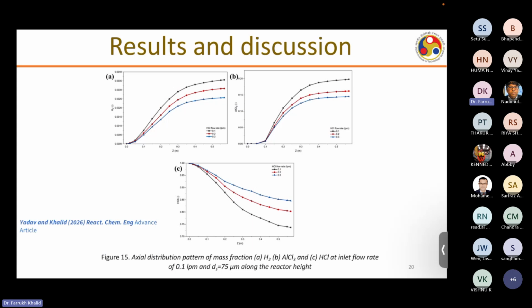Similarly, we also see what is happening when we go along the length of the reactor from the top to the bottom. For hydrogen, if the flow rate is less, then the amount of hydrogen produced is more, because it has more time to interact with the HCl gas and the aluminum particles. As we increase the flow rate, the amount of hydrogen produced is less. As you can see here, as we go up, we find that hydrogen is at the top. So at the top, there is more hydrogen, and similar patterns were observed.